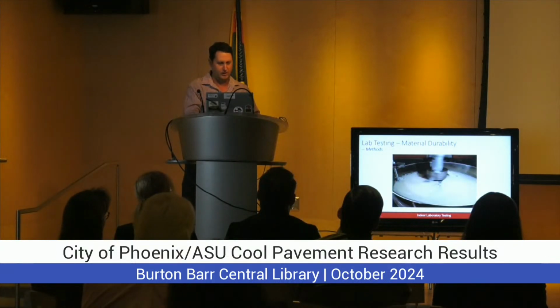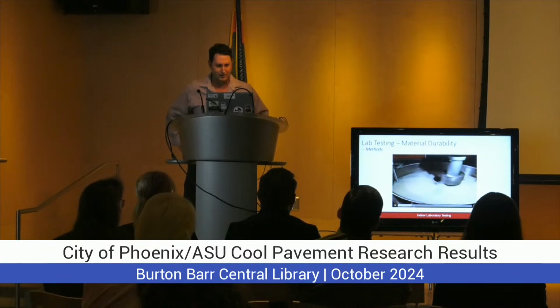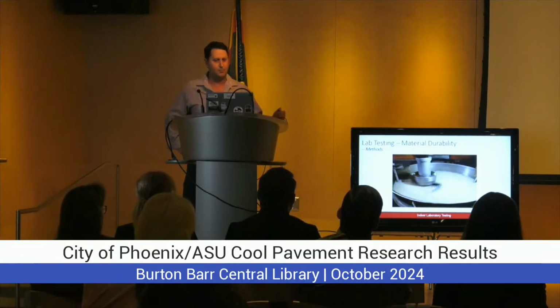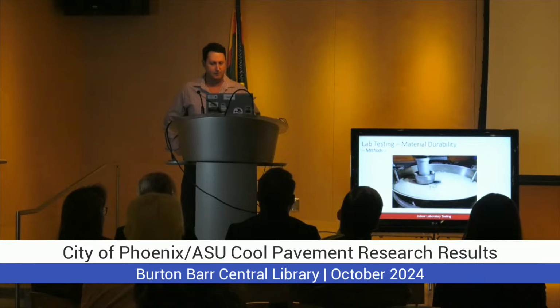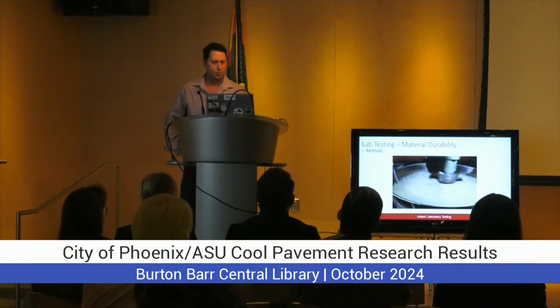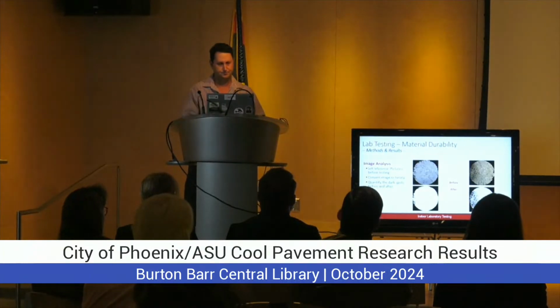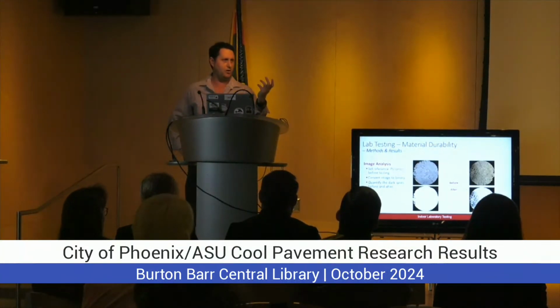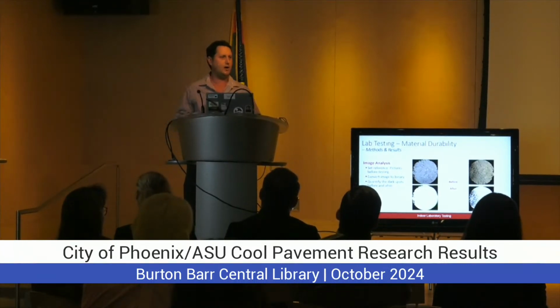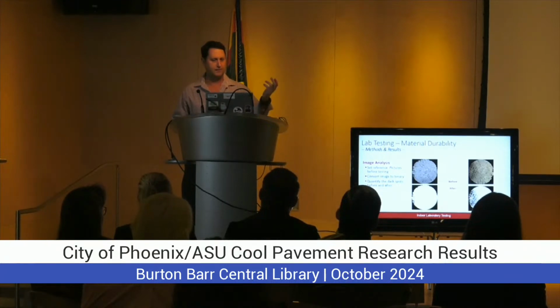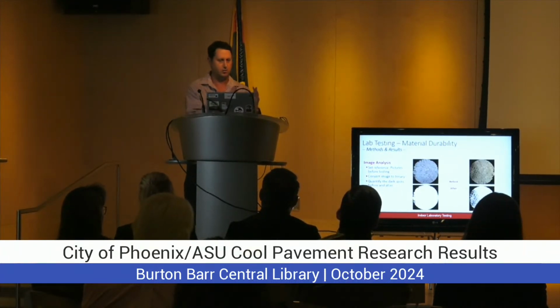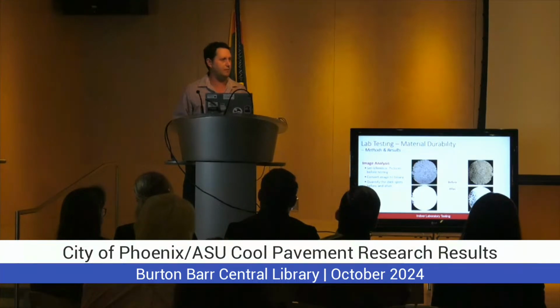And let me show you a quick video of what the test looks like. It's an 8-second video. We condition the sample with heat and everything, and then we place it on the mixer with this brush spinning for 1 hour. The way that we analyze this information is we take pictures before we run the test, and we do an image analysis. You see the picture on the left, on the top, and then the bottom, that's our initial condition. And then after we wear the sample, we analyze basically the black areas in the white and black pictures, and compare the before and after.